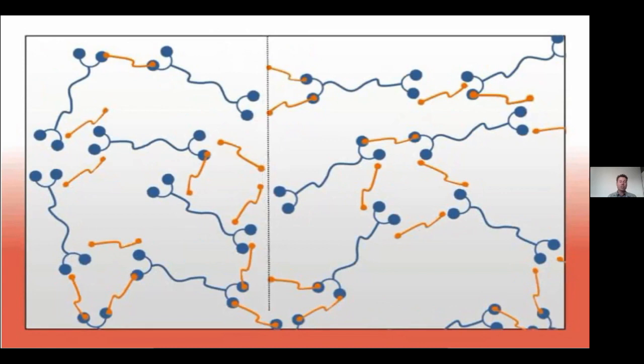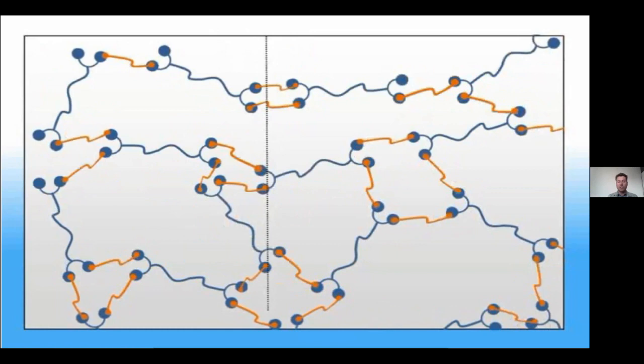And because we decrease the temperature, being reversible, these bonds, they will reform in the network throughout the material, but also across these fracture surfaces, and then everything is healed and the initial properties are completely recovered. So the healing can take place for multiple times. So this is what you can also see if we zoom in. This is a bit fast forward the movie, but you can see that if we increase the temperature, the mobility is increased and we can start healing these damages.